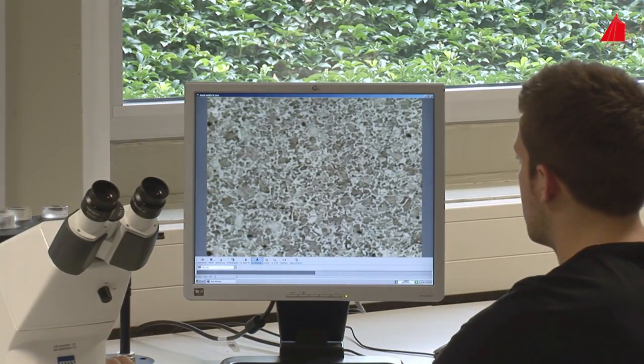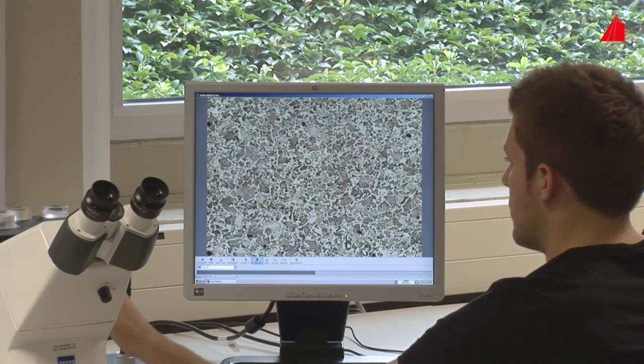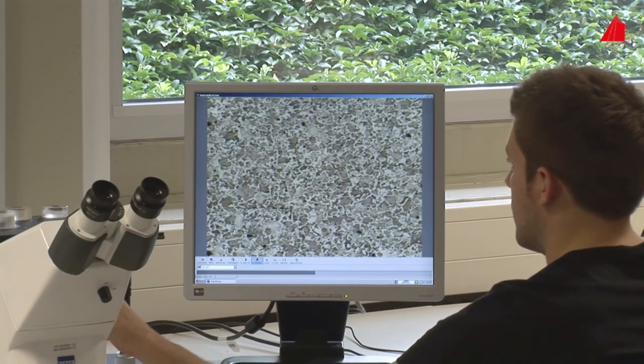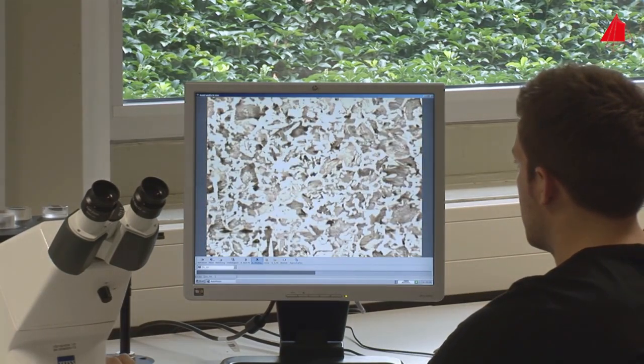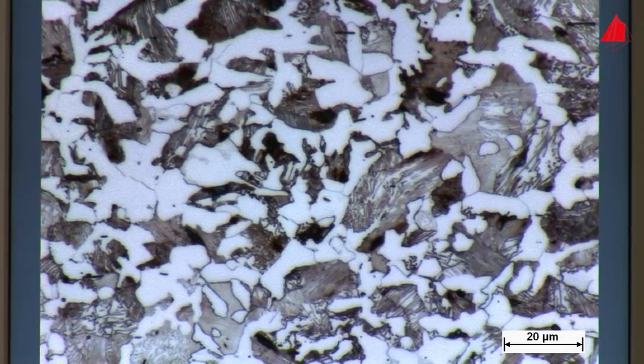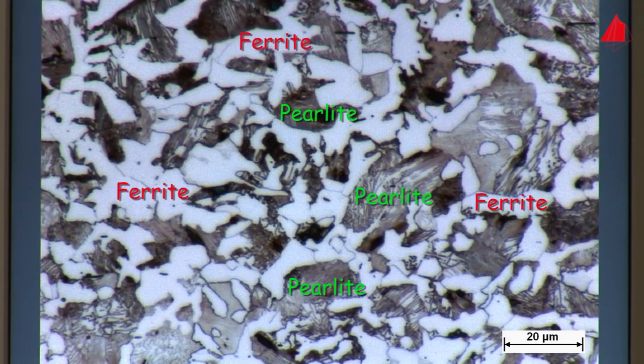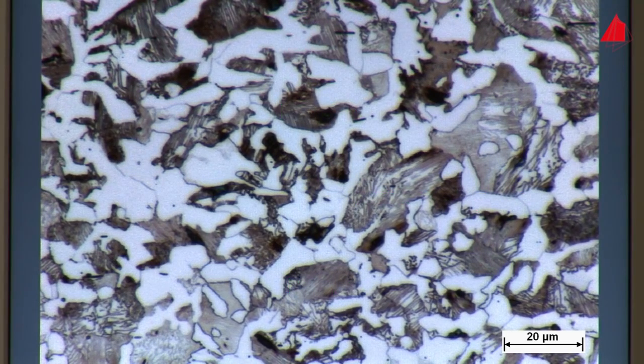In between, he focuses and adjusts the brightness. At medium magnification, light and dark areas become visible. At comparatively high magnification, in some of the dark areas, fine stripes may be recognized. The microstructure in the darker striped regions is termed pearlite. Pearlite consists of thin alternating crystals of ferrite and cementite. The white regions are ferrite crystals. They consist of almost pure iron. Great! The etching has been successful.